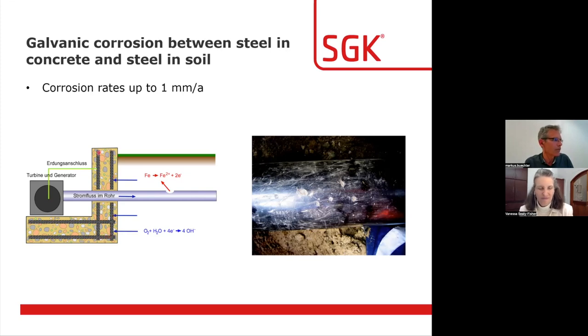Now, I've tried to illustrate here this reinforced concrete structure with the reinforcing steel that is in a passive state and acts as a cathode. On the other hand, we have our pressure pipeline coming from the mountains, being connected to the equipotential bonding and connected to the reinforcing steel. So what we're looking at here is a steel pipeline at a negative potential. It's not quite as negative as zinc, but let's put it at -700 millivolt. And the reinforcing steel in concrete is around -200 millivolts. So it doesn't give you an excellent battery, but it still gives you a battery with 0.5 volt output voltage.